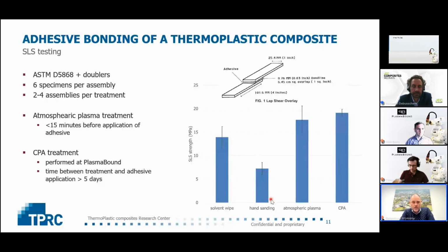Although, say, with 24 specimens, you could argue about statistical relevance for the standard deviation. We can see that the standard deviation on the CPA treated assembly was much lower. These are nice values. They confirm the results that Nick presented and our own experience that you can increase single lap shear strength from, say, 5 to 20 by plasma treatment.